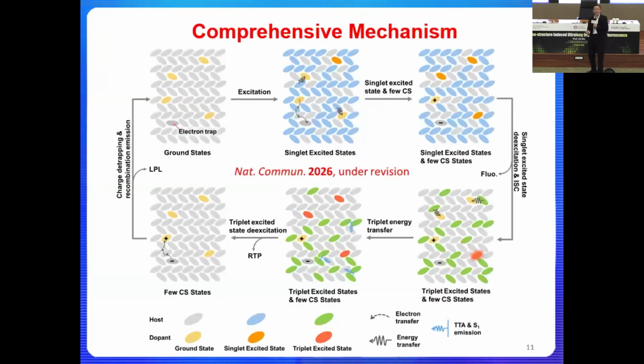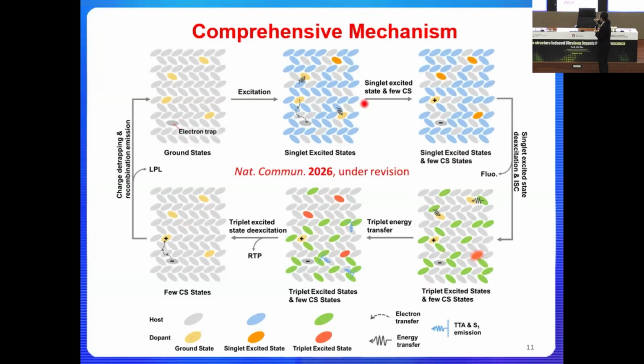So it took us another 3 years, and hopefully in a month or two, you will see this new paper about the mechanism. So even though the two molecules are just simply mixed together, there's a complicated mechanism behind. Long story short, if we look at the mixture, we have these host molecules and a very small amount of dopants. Upon light illumination, we will have the singlet excited states and a small amount of the charge separate state. But because the dopant number is very small, you can imagine the number of charges formed in the charge separate state is very minimal.